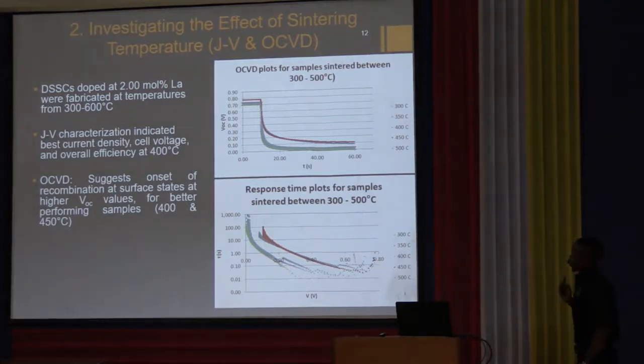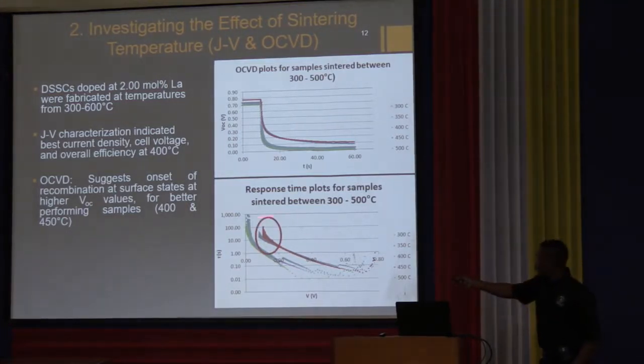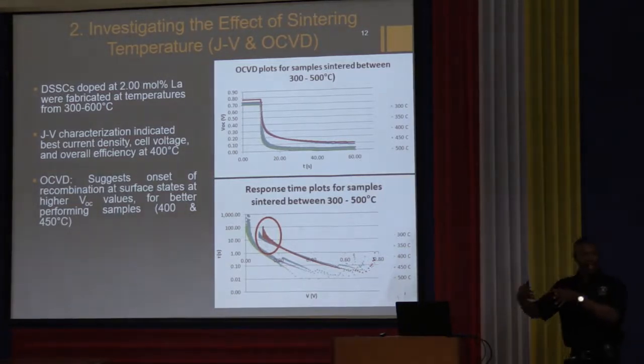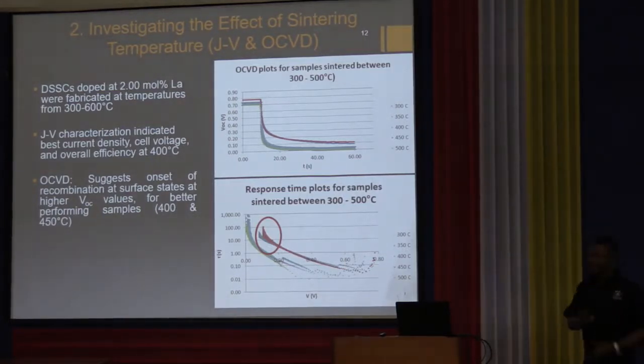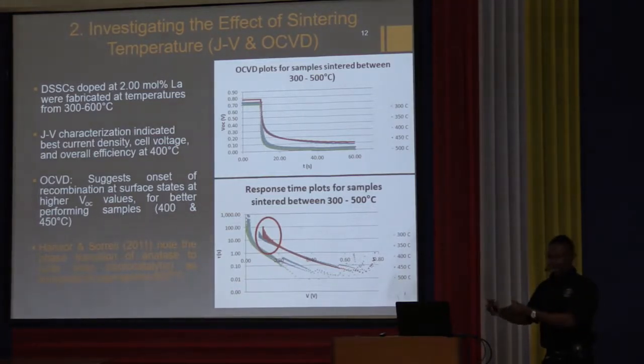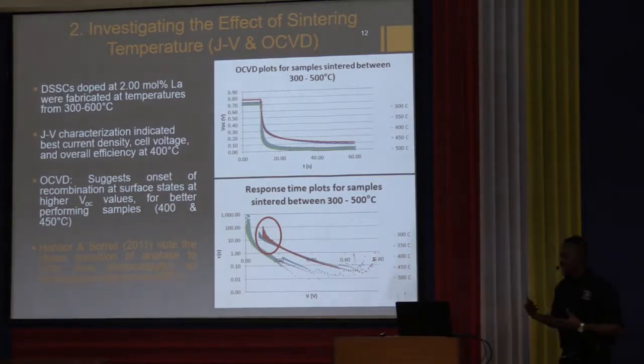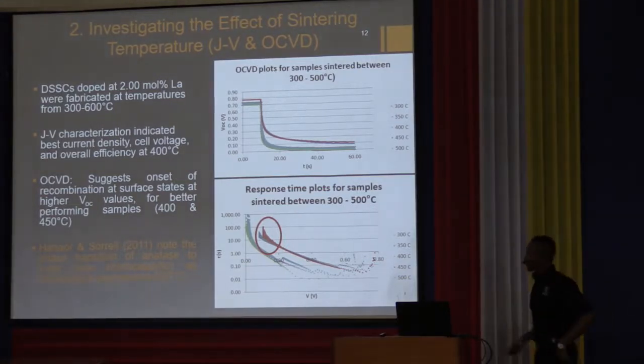Another analytical technique we used was open circuit voltage decay. And for the two best performing samples, this characteristic peak from the open circuit voltage decay graph is shifted, and this is correlated to a shift in how the cell recombination is affecting the cell performance. This again tells us there's something special about these two particular temperatures that we used for sintering. Now, it's been noted in literature that as you heat titanium dioxide at higher temperatures, the crystal phase moves from a highly catalytic form to a less catalytic form. And the less catalytic this form is, the less the push for electrons around the circuit is, which could again explain the reduction in performance that you see at higher sintering temperatures.